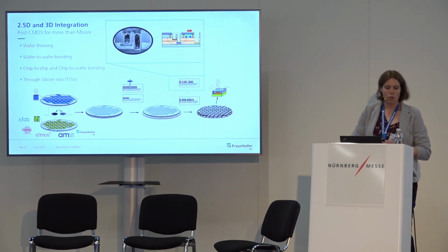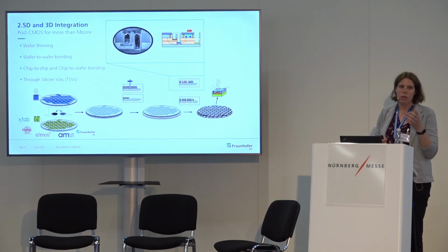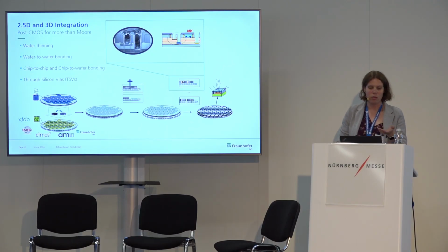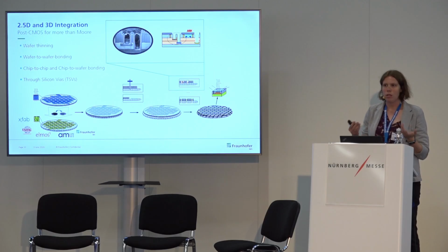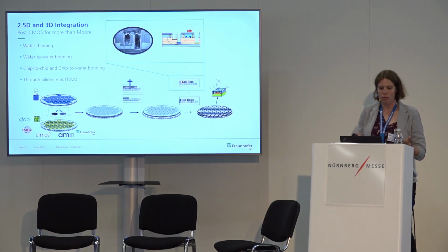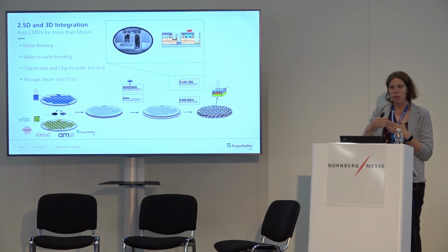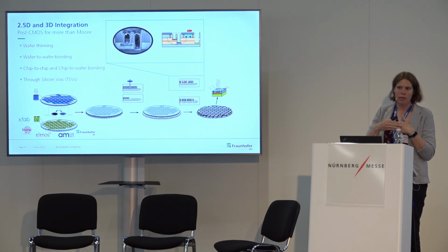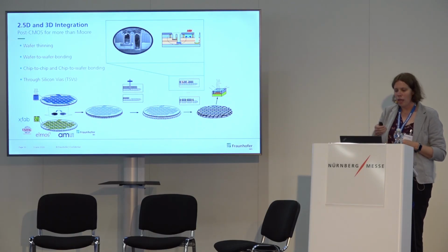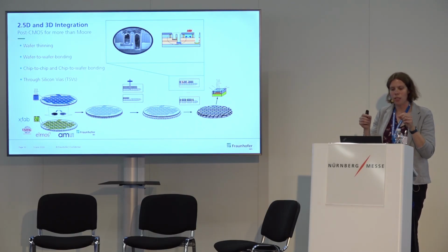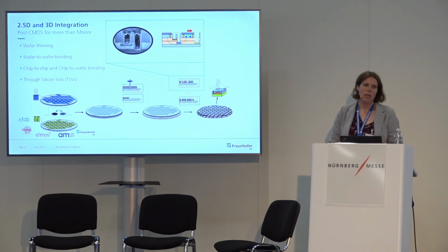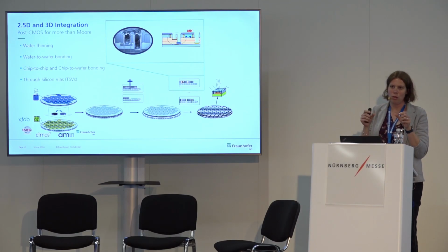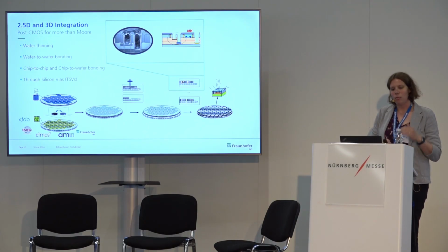This 2.5D and 3D integration is one part. Here we have the possibility to have any kind of readout wafer. This could be a Fraunhofer internal readout wafer, but it could also be a wafer from X-FAB or Tower or wherever. And then we have our MEMS wafer on top, and we can combine them by wafer-to-wafer bonding. And then we are doing the interconnections through silicon vias. There we are etching from the top wafer down to the bottom wafer to get the contacts. And here we are using especially our ALD technology to get a really good contact from the top wafer to the bottom wafer.